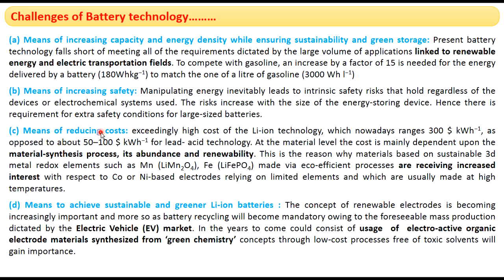Another major challenge is reducing the cost of batteries. Current lithium-ion battery technology is expensive compared to lead-acid technology — lithium-ion technology spends $300 per kilowatt-hour, whereas lead-acid technology spends only $50–$100. At the material level, cost depends on material synthesis process, abundance, and renewability. This is why materials based on sustainable metal redox elements such as lithium manganese oxide and lithium iron phosphate, made via eco-efficient processes, are receiving increased interest compared to cobalt or nickel-based electrodes.